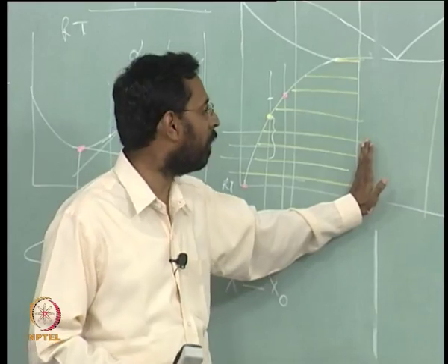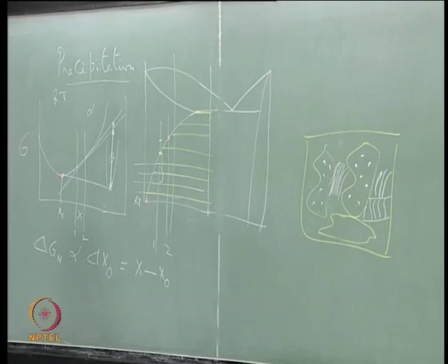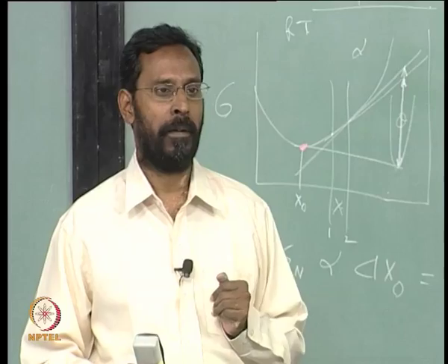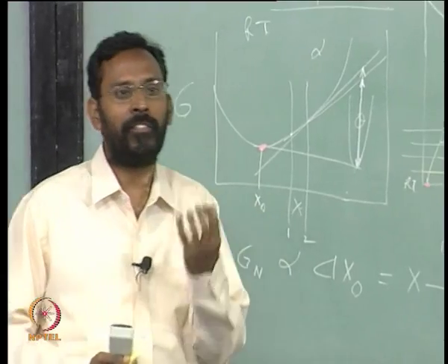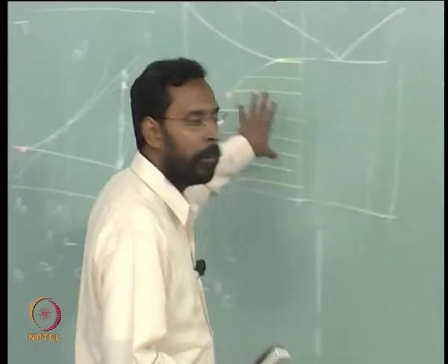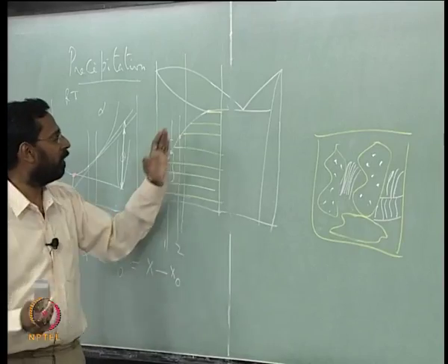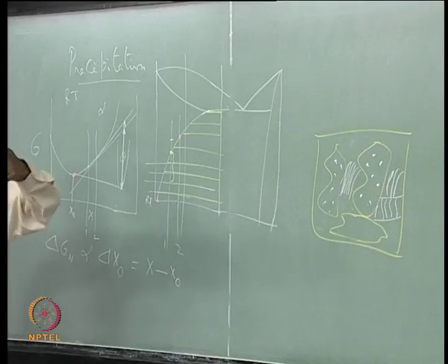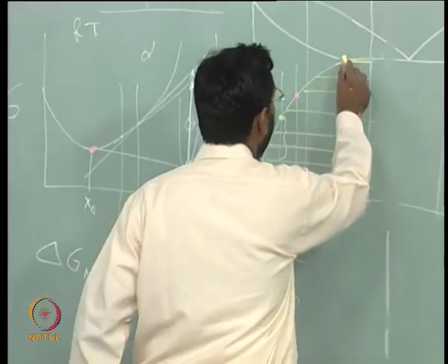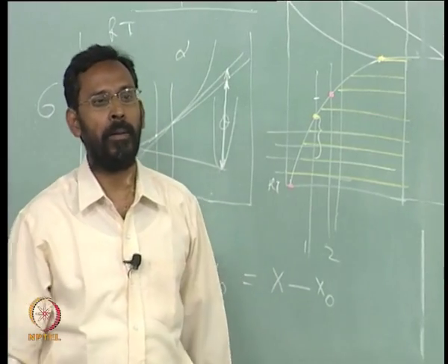This kind of composition is not ideally suited for age hardening, because you will somehow have some prior theta formed during solidification, and as a result the full advantage of age hardening, which is a combination of ductility and strength, is not possible to achieve. So you always try to restrict to, let us say, 4%, 4.5%, 5%. In fact, though I say this is the limit, in principle you do not even reach there, because there is another problem associated with it.